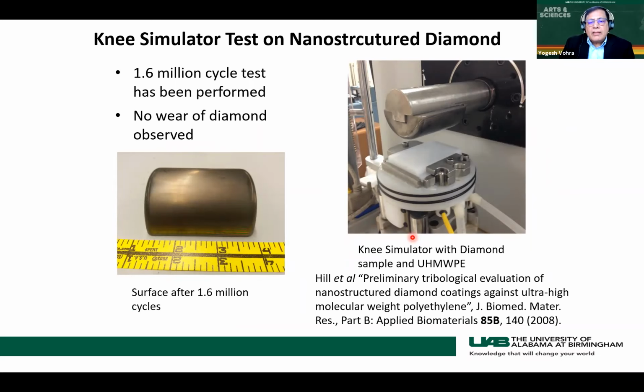So one obvious application for these materials is in biomedical joints, like hip and knee joints, where you want low surface friction and minimal wear. So we basically translated this technology into diamond coating on curved surfaces, like a knee simulant. And then we actually put this diamond coated implant into a knee simulator, where it articulated against ultra high molecular weight polyethylene, which is the current industrial standard of using metal on polymer couples. And here we show that this remains adhered after 1.6 million cycles, which is about 1 year of clinical use, with no delamination.